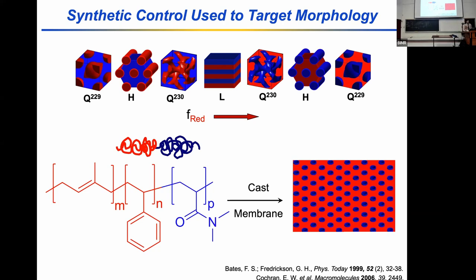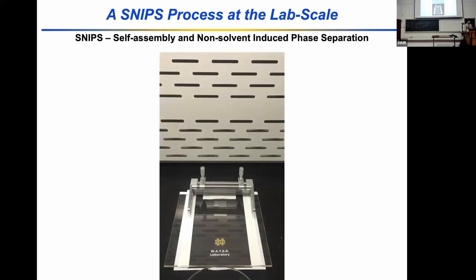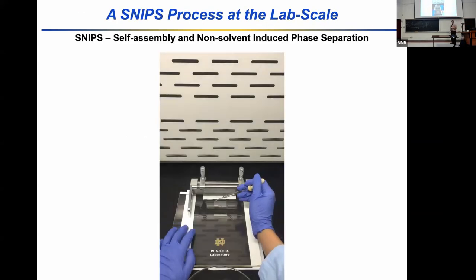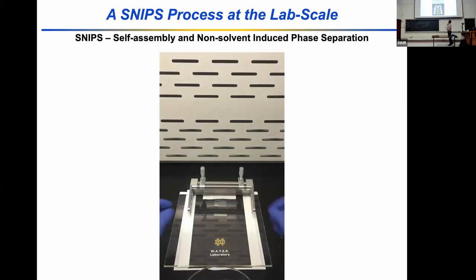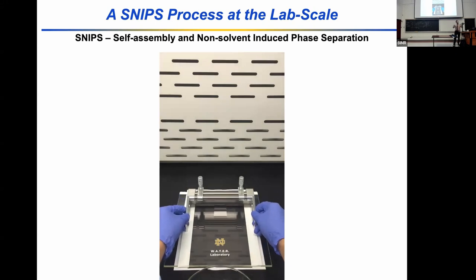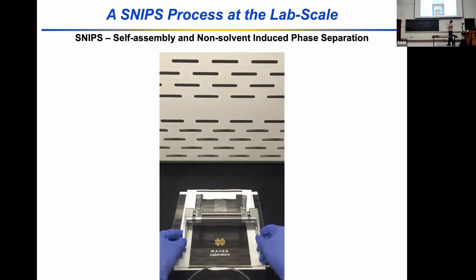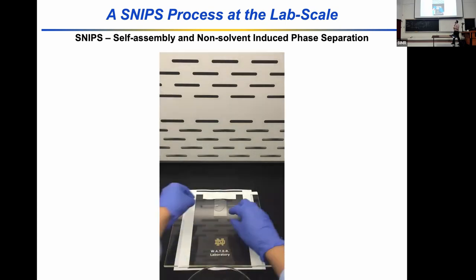I will be happy to talk to anyone about the technique after, but we've spent a lot of time thinking about what solvents we need to pick to do this, as well as what evaporation times and what evaporation rates need to be utilized to direct the self-assembly of this hexagonally packed cylinder. But once we optimize for all of those conditions, when we operate the technique in the lab, it looks very similar, I would argue, to what you do for the commercial casting process. There's our homogeneous solution. We use a hand-pulled doctor blade instead of the blade coater that's used at the commercial scale.